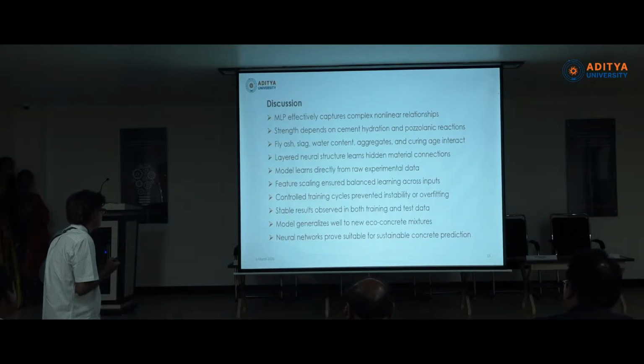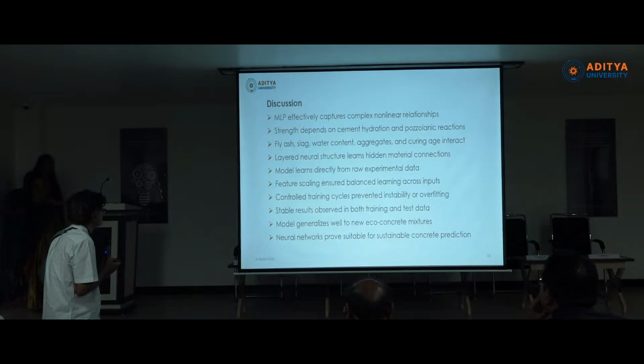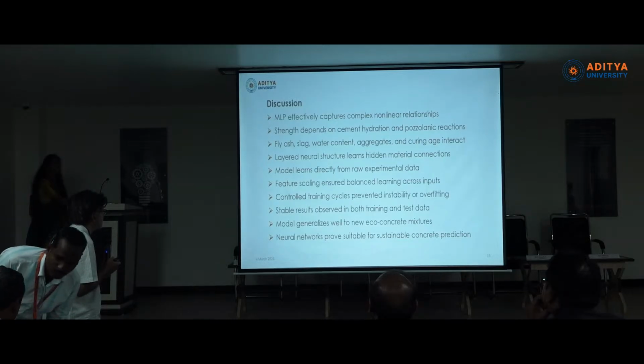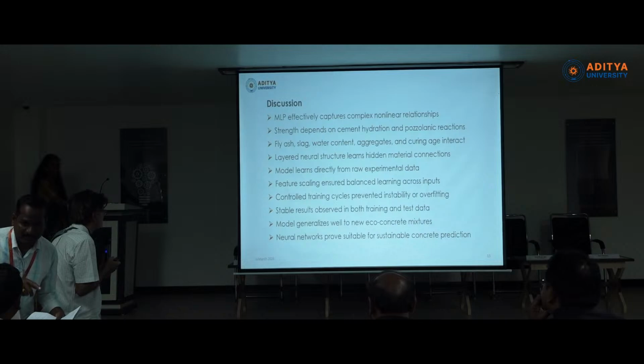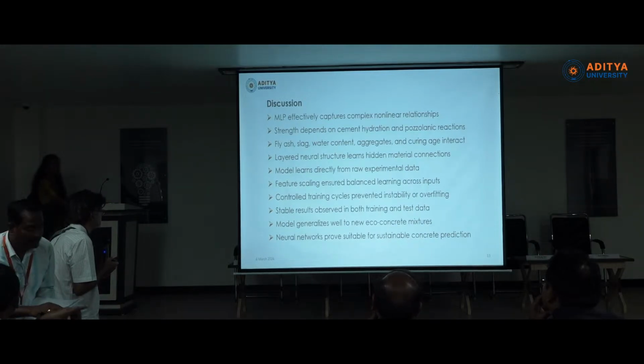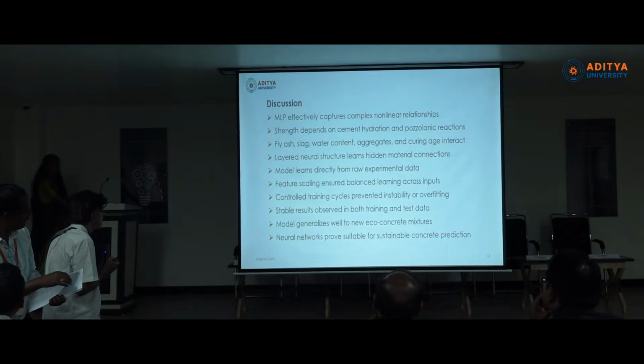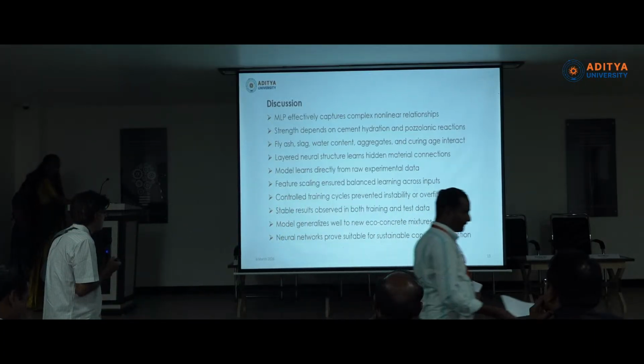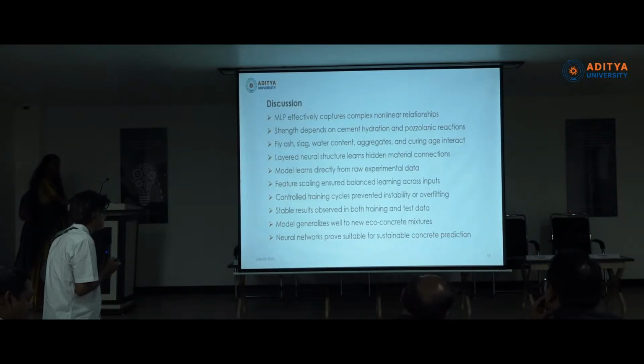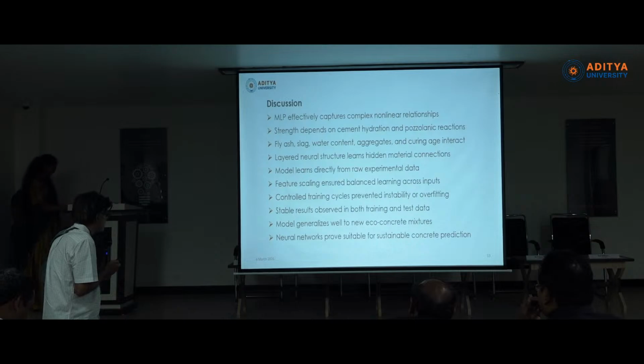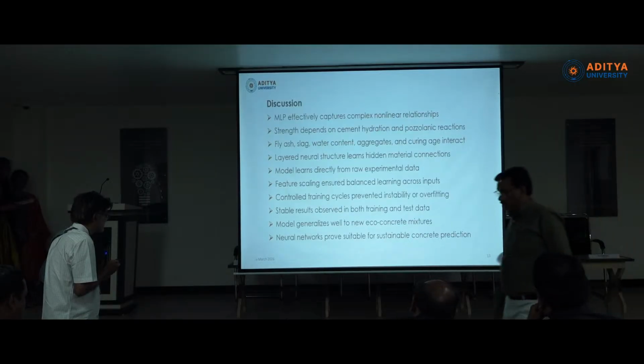Discussion. MLP effectively captures complex nonlinear relationships. Strength depends on cement hydration and pozzolanic reactions. Fly ash, slag, water content, aggregates and curing age interact. Layered neural structure learns hidden material connections. Model learns directly from raw experimental data. Feature scaling ensured balanced learning across inputs. Controlled training cycles prevented instability or overfitting. Stable results observed in both training and test data. Model generalizes well to new eco-concrete mixes. Neural networks are suitable for sustainable concrete prediction.